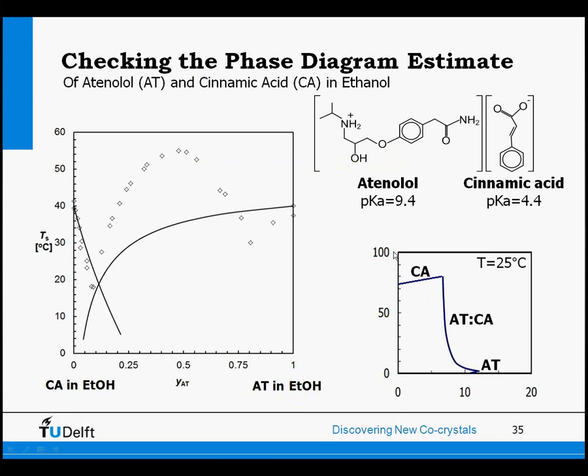That things do not always work, you see in this diagram, where we determined in a similar way as in the previous slide the phase diagram for Atenolol with Cinnamic acid. And you see that Atenolol has a very high pKa and Cinnamic acid has a low pKa, so they must form a salt if they crystallize together into one crystal. And you see that if you have dissociating molecules here, then you might end up with a large deviation.